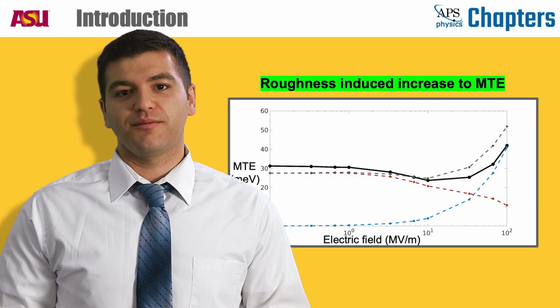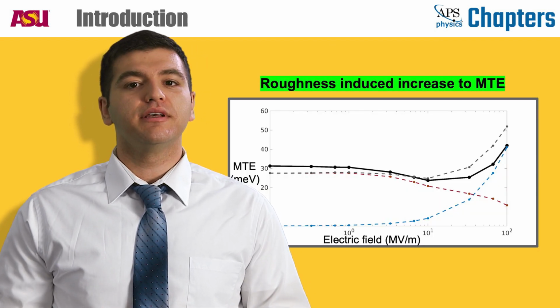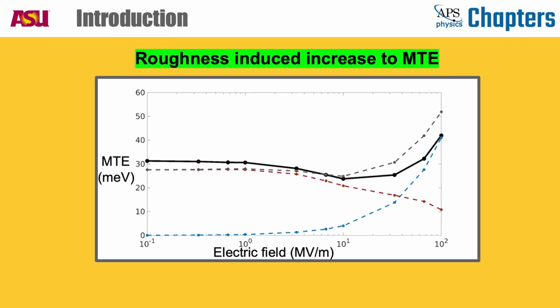So what did we learn from this code? The code outputs this plot where the black solid line is the estimate of the combined roughness effect on MTE versus the strength of the electric field. This work showed us that the roughness of polycrystalline photocathodes could contribute to the MTE as much as the temperature effect. This happens both at low fields and high fields, and the only way to get away from this is to not have roughness by using epitaxially grown or single crystalline ordered surface photocathodes.